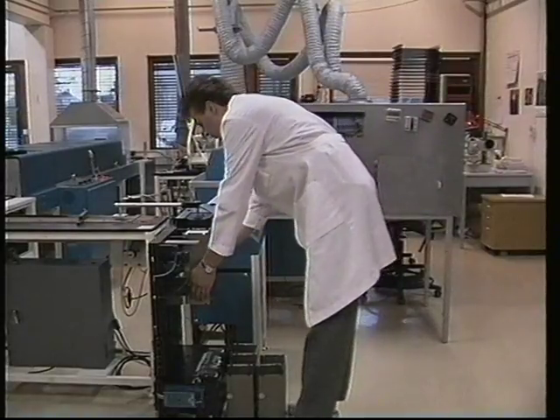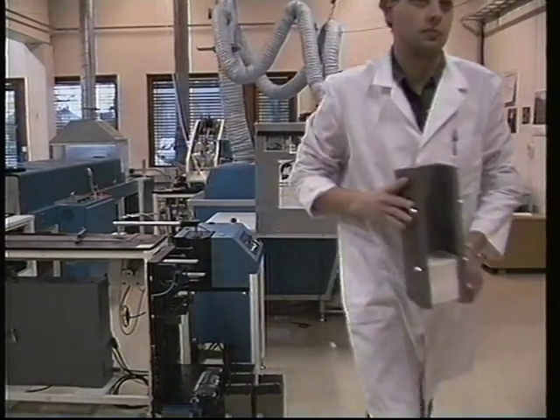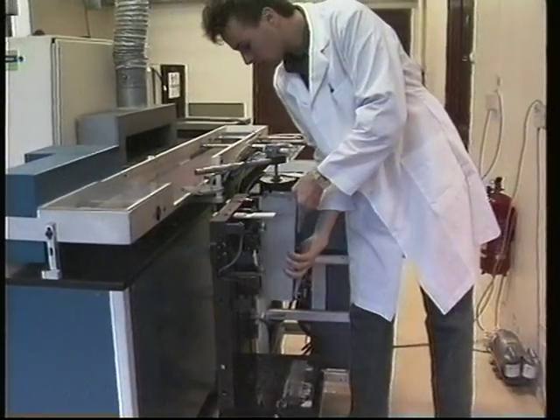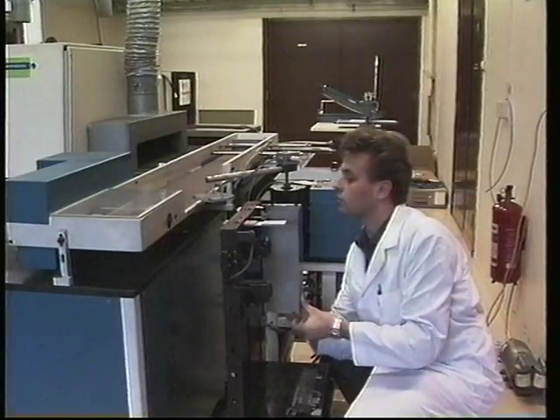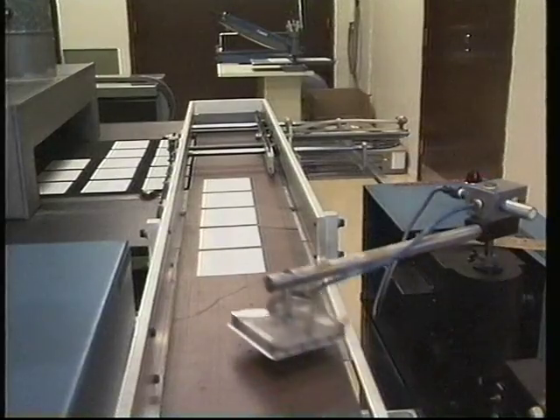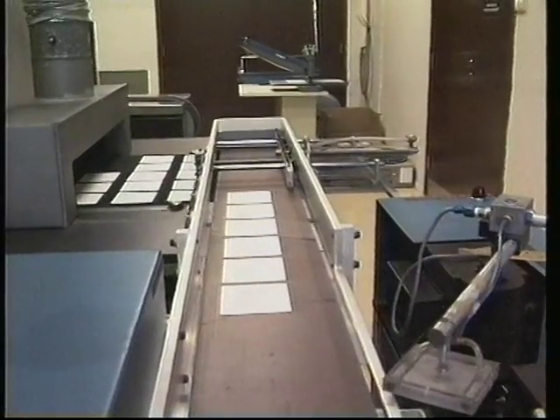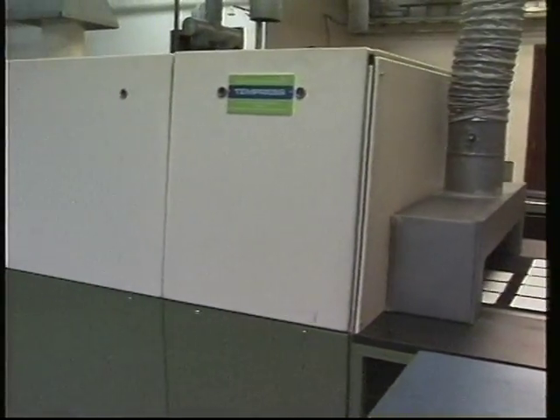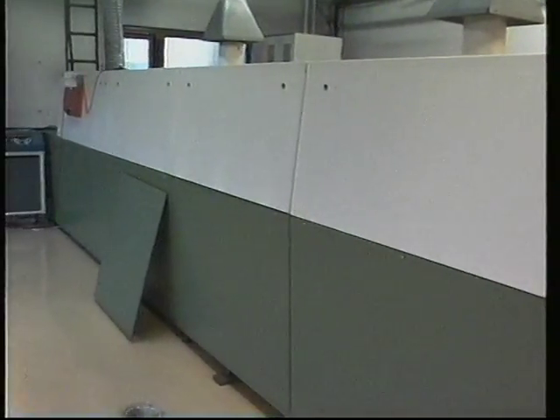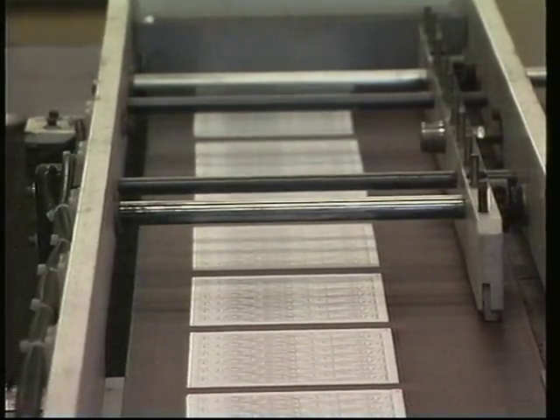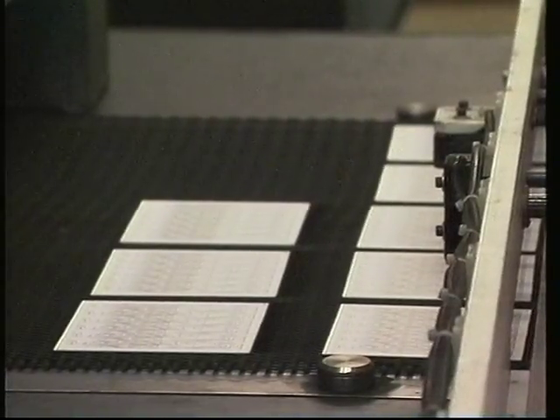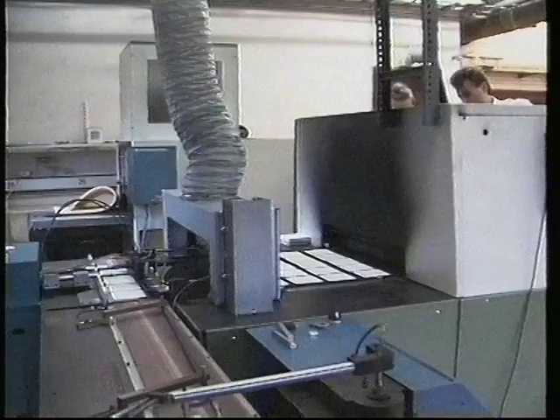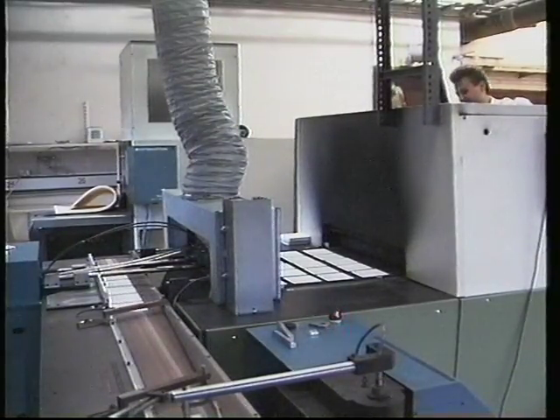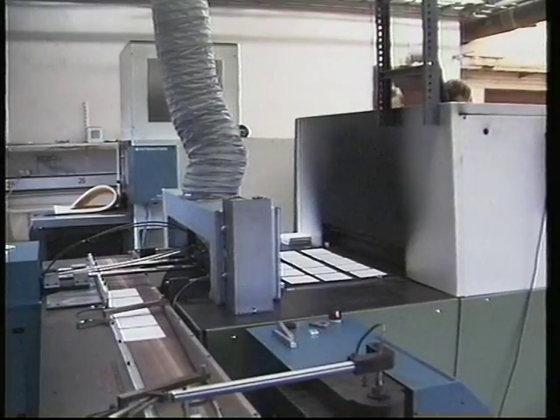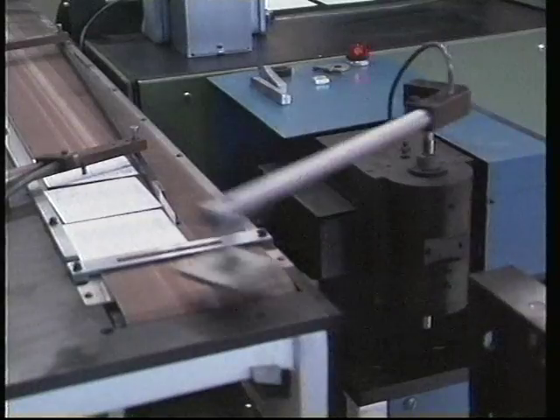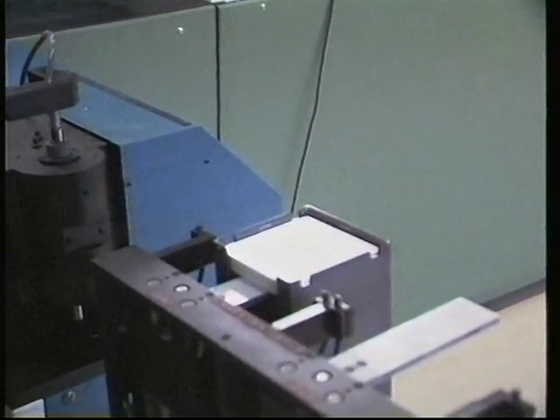The cassette is necessary for subsequent automatic handling. In this furnace, the printed layer is cured or fired for another 10 minutes at a temperature of 850 degrees centigrade. Organic filler material in the printing paste evaporates. The glass particles in the paste will melt and make a very stable matrix for the conductive metal particles. The metal may be a silver palladium alloy, and the conductor will be about 15 micrometers thick after firing.